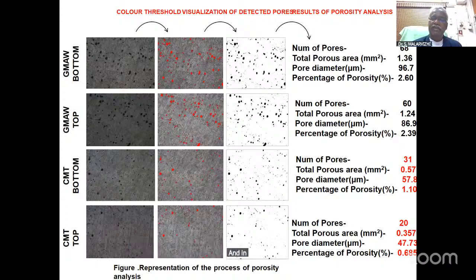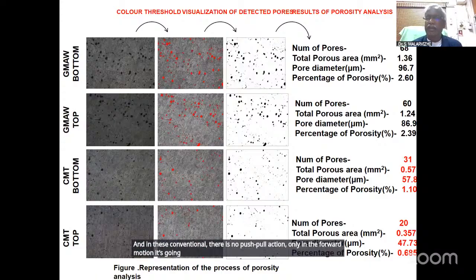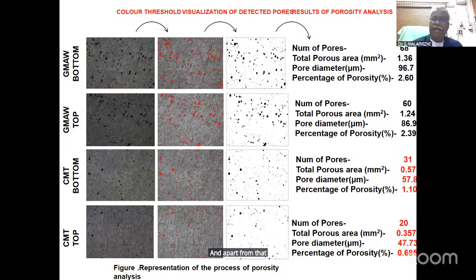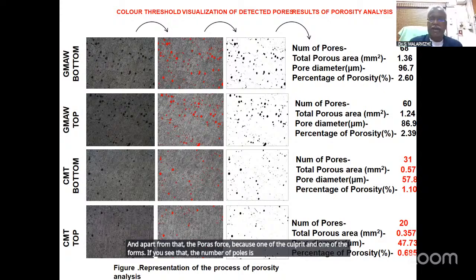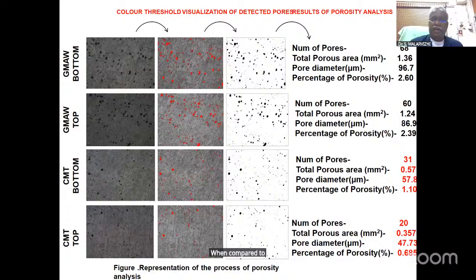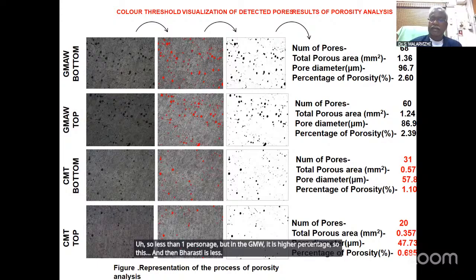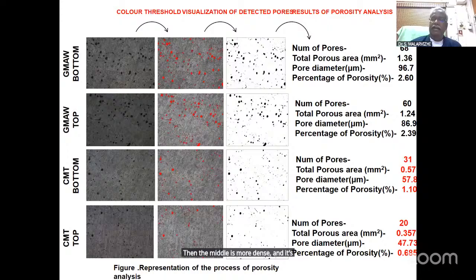In the conventional GMAW, there is no push-pull action, only forward motion, so the heat input remains constant. And that action in CMT produces fine grains. Apart from that, in aluminum alloy, porosity is one of the culprits. If you see, the number of pores is greatly minimized in CMT when compared to the GMAW process. The percentage of porosity in CMT is less than 1%, but in GMAW it is a higher percentage. So the porosity is less, the material is more dense and harder, and it increases the strength.